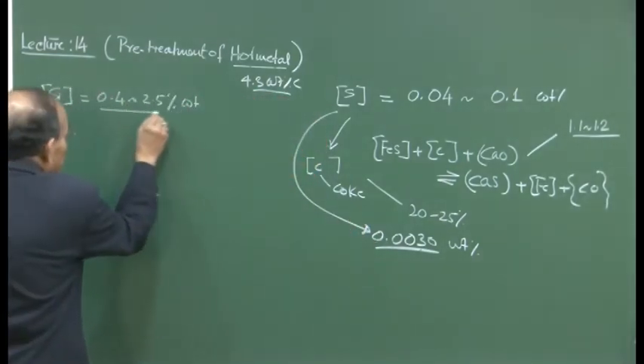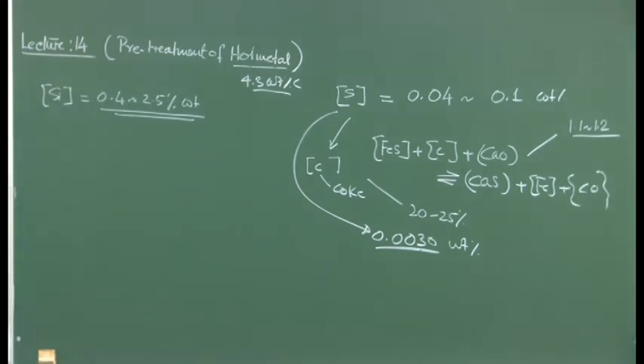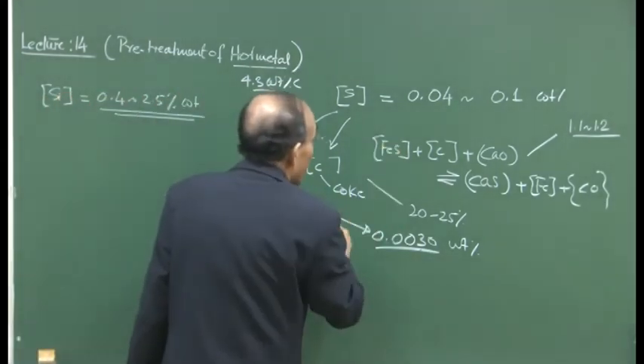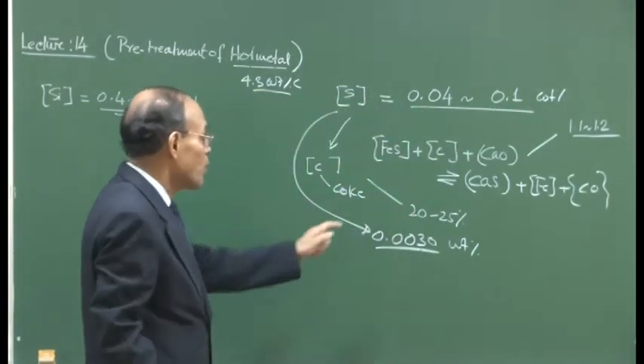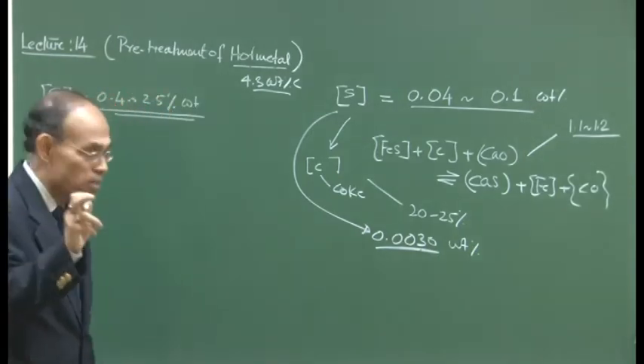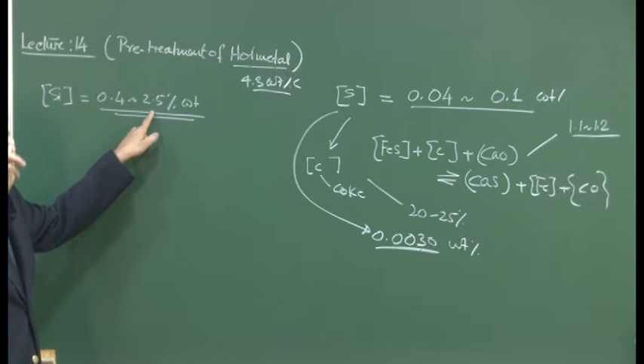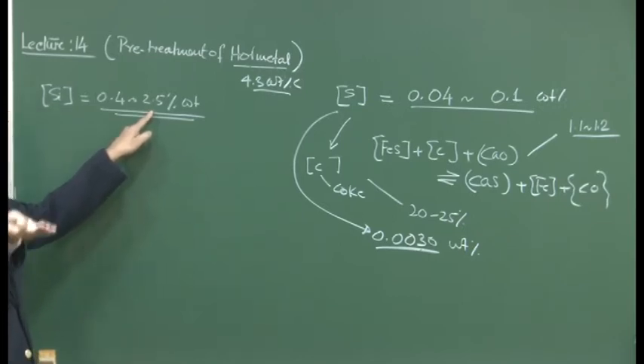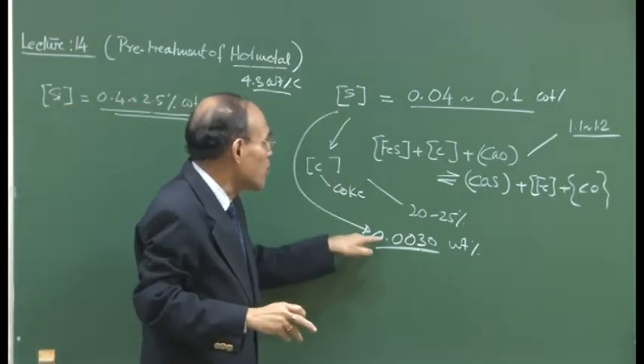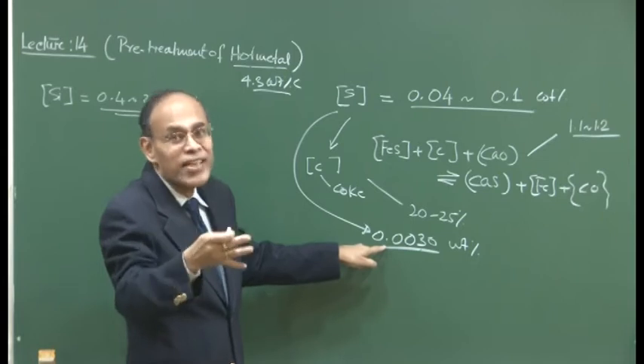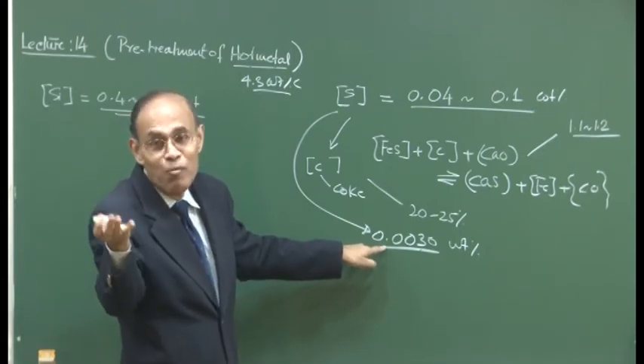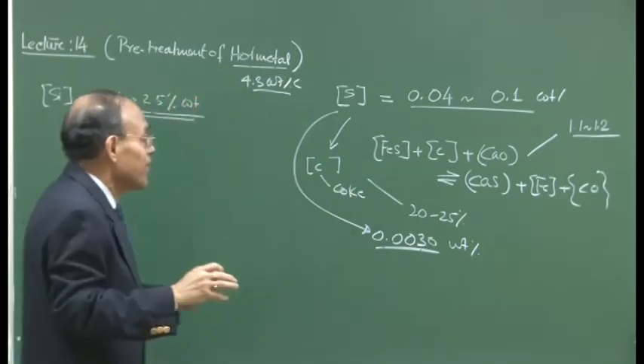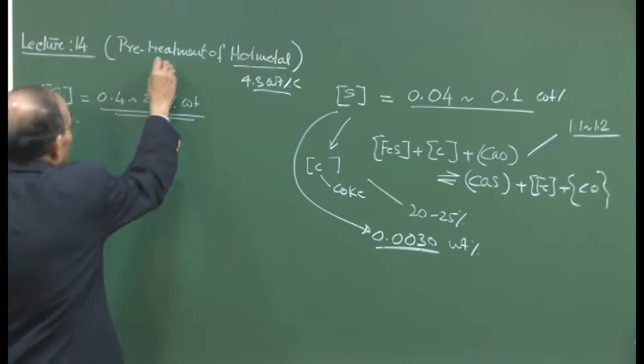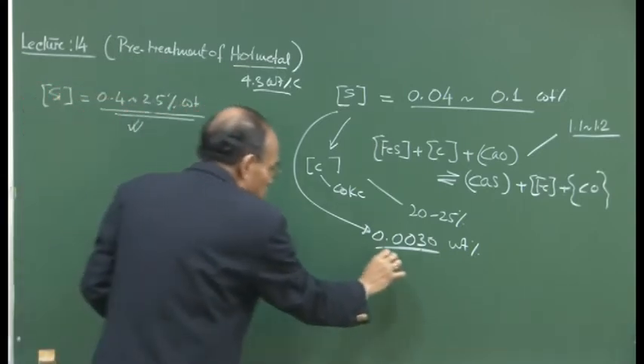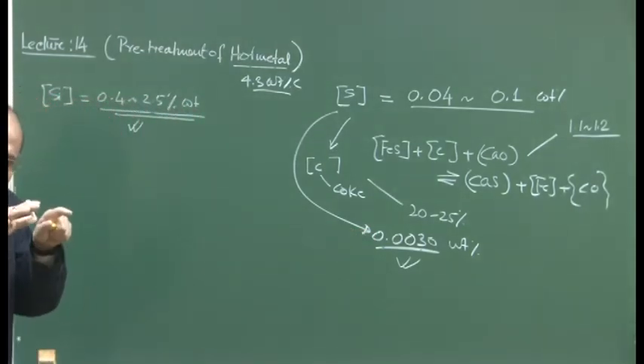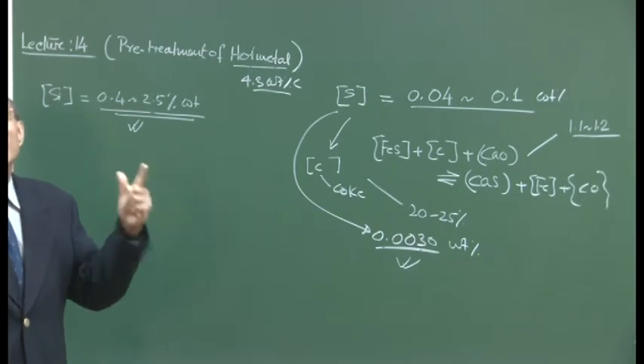So, silicon could be very high in the pig iron, and also the sulfur could be very high. This is the range of sulfur. On the other hand, we require a very small amount of sulfur itself, and the presence of high silicon will jeopardize the steel making operation because of extremely high temperature, and a very high sulfur content in the pig iron will be disadvantageous as far as steel making is concerned, because steel making is an oxidizing environment, we cannot eliminate sulfur. So, it is therefore imperative that before we do steel making, attempt must be made to control silicon, attempt must be made to control sulfur and bring it to a more or less acceptable limit, and that should be the starting point for steel making.